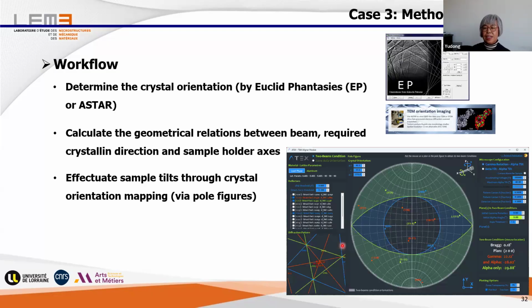Okay, so the software looks like this inside, and we express all these relations with the pole figure. You see, we have different zones with different colors, and these different zones tell us the angle limits of the TEM holder, because in TEM we cannot turn the sample from 0 degrees to 90 degrees. With different zones, either such a zone is single tilt, either x direction, alpha tilt, or this is where we need a double tilt. So for zones like this, and zones like this, we will never reach any condition. Then we have to abandon, and we have to search for something else.